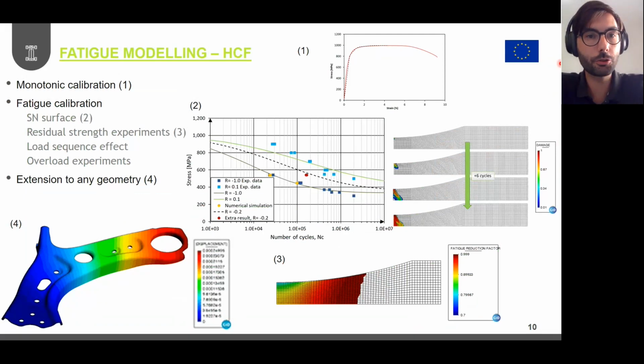Okay, so how do we use this model? Well, as I said before and during the Fatigue4Light presentations, during the project, we have done an experimental campaign to be able to characterize in monotonic and in fatigue terms the different materials that we are using, like aluminium, steels, and so on. So we need the monotonic calibration for the stiffness and strength, and fatigue calibration for estimating the different material properties related to fatigue. And with that, we can apply the numerical model to any geometry, thanks to the spatial discretization of the FEM, like we can see in the lower left figure of the lower control arm.